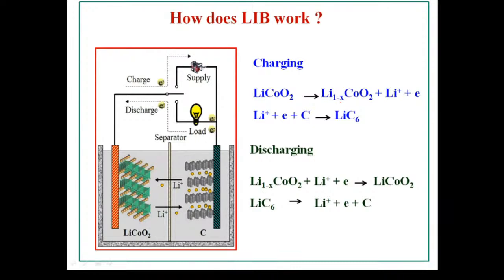Now see one point: whenever lithium ions are extracted from lithium cobalt oxide, there will be shrinkage in the volume of the crystals, and whenever lithium goes inside the graphite interspacing, the spacing between the graphite layers will increase. So there will be some mechanical stress. And over a long time, that's why our mobile fails after a couple of years, say 4 years. You see that the battery is not working. Basically, due to these mechanical stresses and strains, a kind of breathing takes place, and the material pulls away from the current collector.